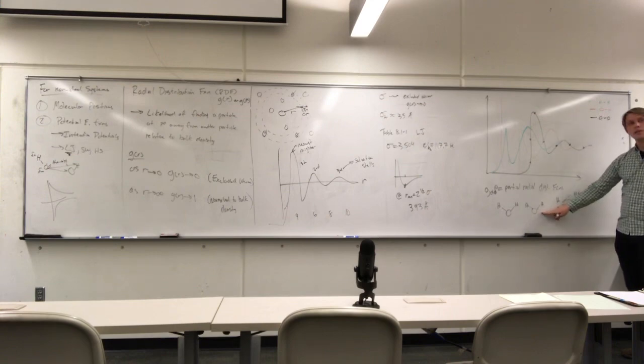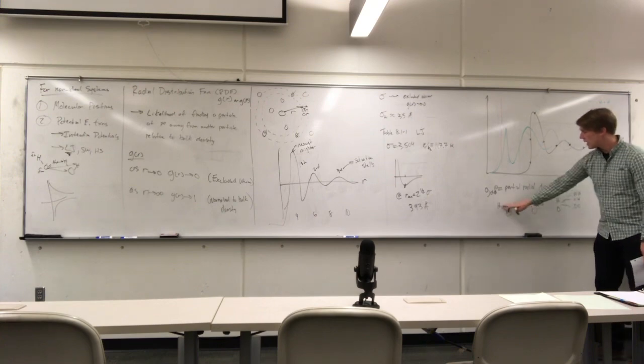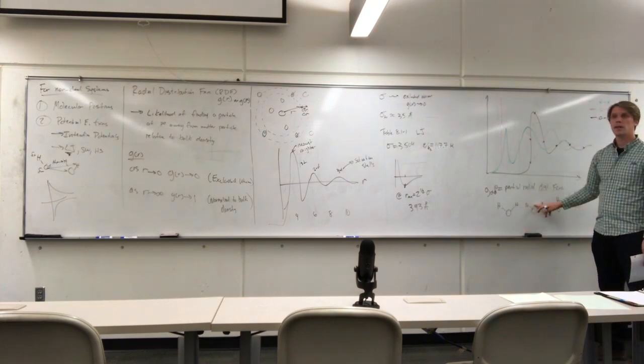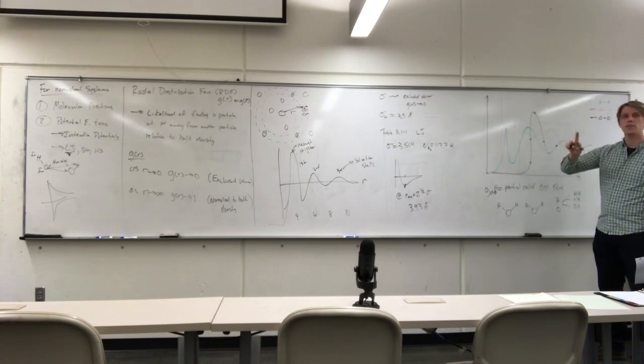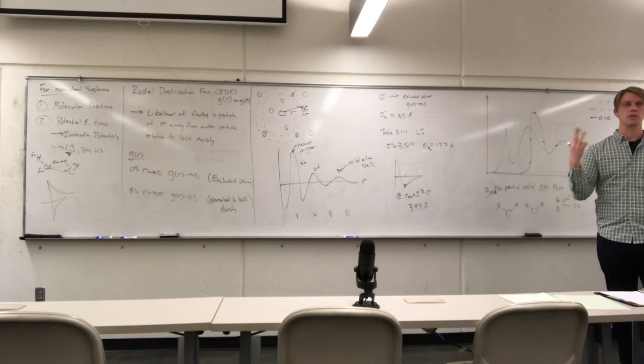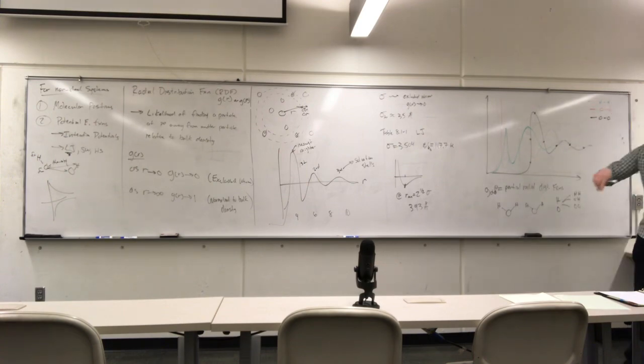But the cool thing here is that if I do a hydrogenated water scattering pattern, a deuterated water scattering pattern, and a mixture of hydrogenated and deuterated water scattering pattern, then that gives me 3 overall structure factors that I can then Fourier transform to give me 3 partial radial distribution functions. So we're going to talk a little bit more about scattering theory as time goes on, but I wanted to introduce how this plot was actually generated.